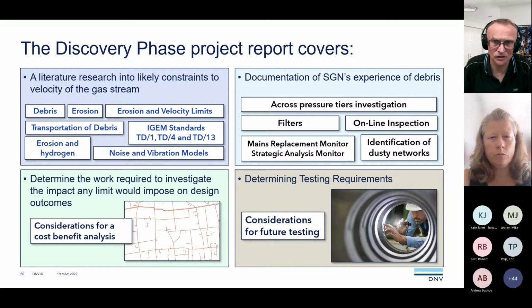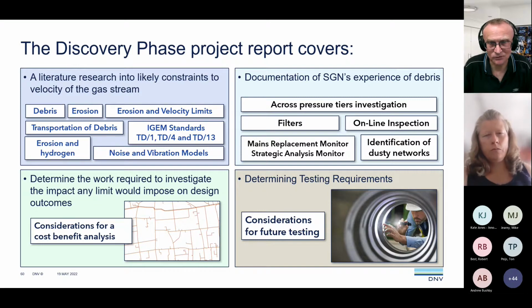So the second aspect on the right there is, because we did this project with SGN jointly, what debris is doing in the networks. SGN did some investigating, and we've been trying to correlate this across all the different pressure tiers in the different networks. What have they found? What's the operational experience of finding bits and pieces in filters? When they do inspection vehicle runs, what comes out? When they do mains replacement, so they're replacing a lot of iron pipe, what's coming out of the iron pipe? And which network's basically got a lot of dust and other debris inside them, and is that related to pressure?